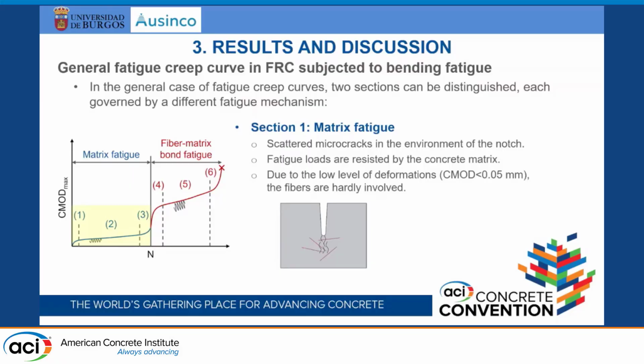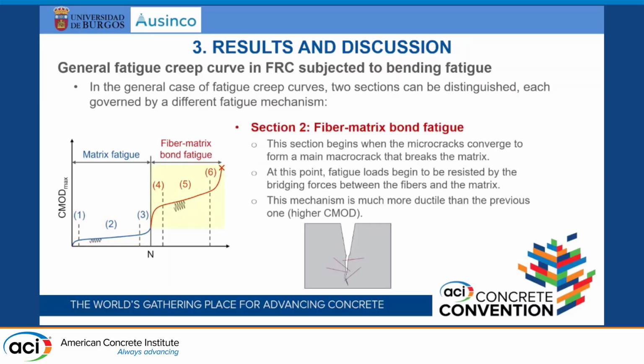First, we have a region of matrix fatigue. In this region, remember, in uncracked concrete, there are scattered microcracks along the notch, and fatigue loads are mainly resisted by the matrix itself. So the fibers, due to the low deformations, are not involved. And what happens once we reach this point, which is more or less the crack point? The fiber-matrix bond fatigue starts. All the microcracks converge in a main crack, and fibers start to actually work, with the adhesion between fibers and the matrix. Obviously this mechanism is much more ductile, and that's why we have more variation in CMOD. We go to more CMOD until the final failure of the specimen is reached.